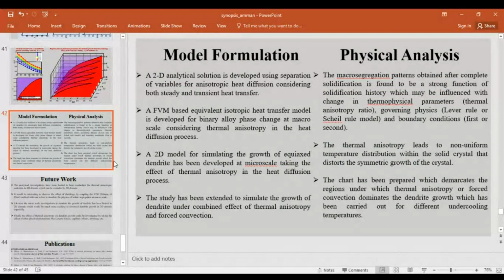In the model formulation, a 2D analytical model has been developed using the separation of variables method for anisotropic heat conduction, considering both steady and transient heat transfer. Then an FVM-based equivalent isotropic heat transfer model is developed for binary alloys at macro scale, considering the diffusion process. A 2D model for simulating the growth of equiaxed dendrite has been developed at micro scale, taking the effect of thermal anisotropy in the heat diffusion process. Finally, the study has been extended to simulate the growth of dendrite under the combined effect of thermal anisotropy and forced convection.